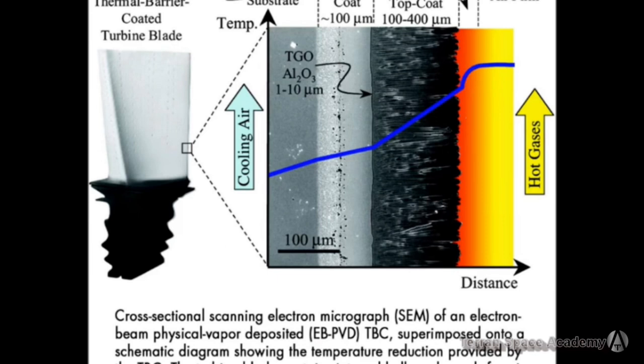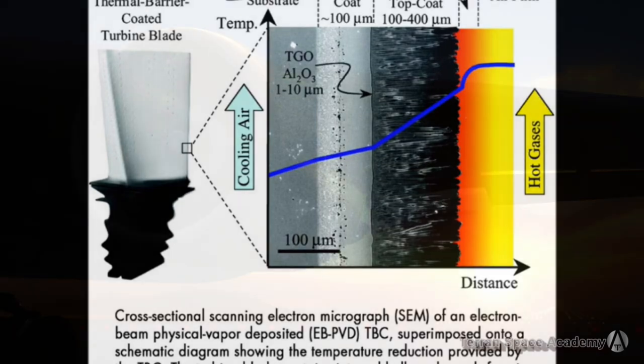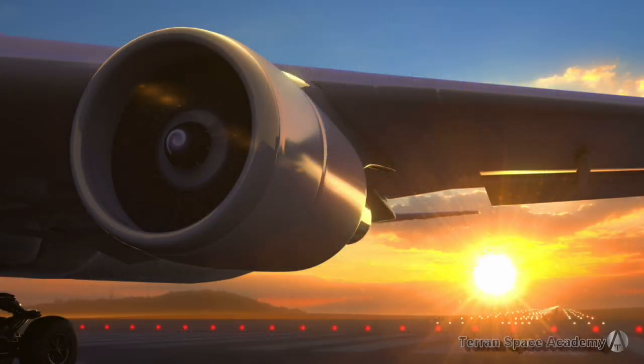This cooling air is around 650 centigrade, but that is well below the melting point of this nickel alloy, and it forms a sheath of cool air around the blade. This keeps the blade temperature in these engines at around 1150 centigrade. They can easily handle this. Modern jet engines are one of the most refined and dependable machines ever built by humans.